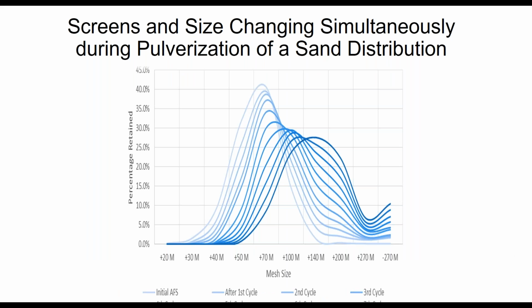And what we do at Western Michigan University, because these are some non-standard approaches that have been placed at the forefront of AFS to consider, we look at a distribution of sand and we try to break it down according to the typical ways the foundry industry has that depreciation of that sand. And the two major mechanisms is really impact and abrasive wear. Those happen time and time again through molding, melting, and filling, certainly at ambient, through elevated temperature.